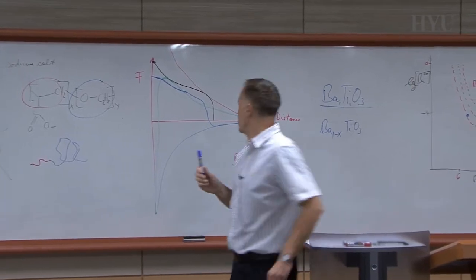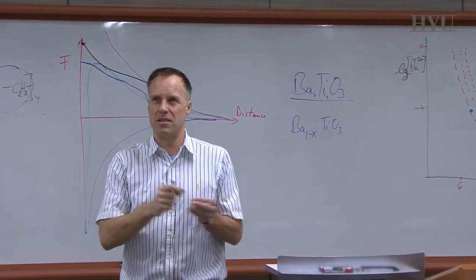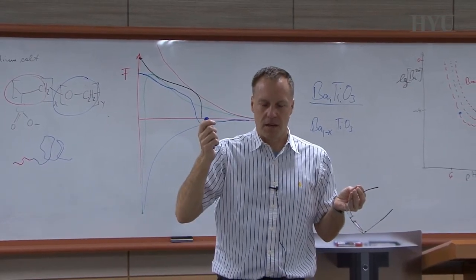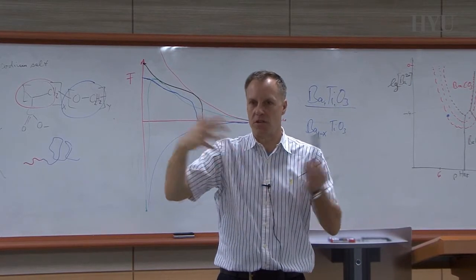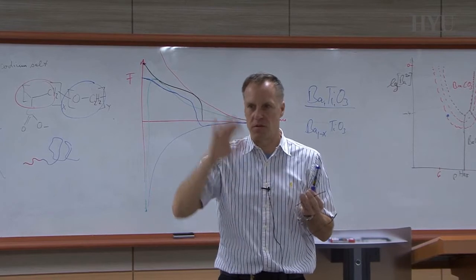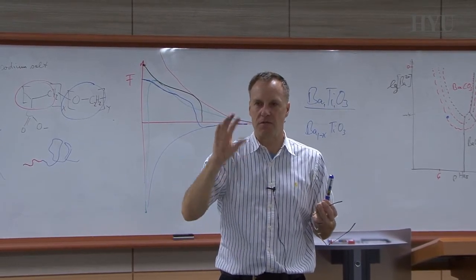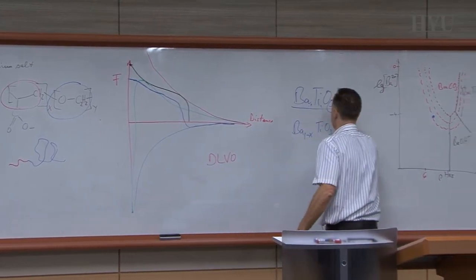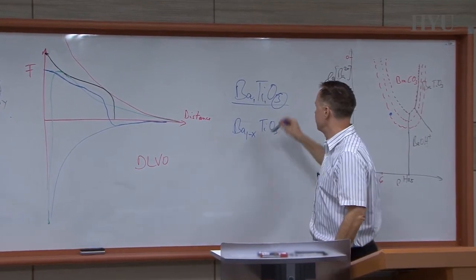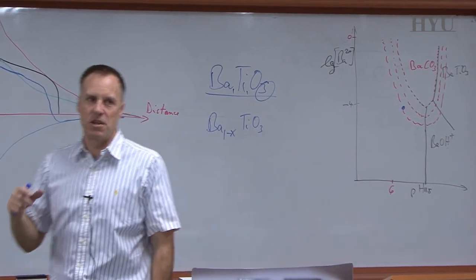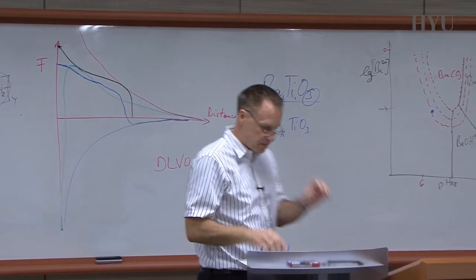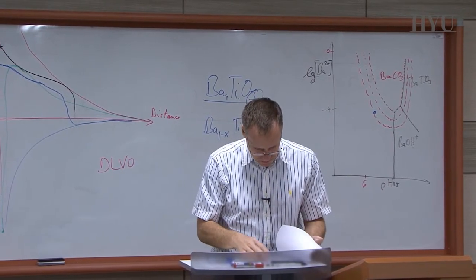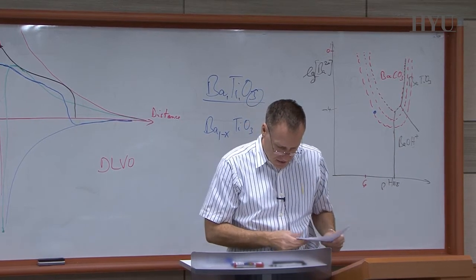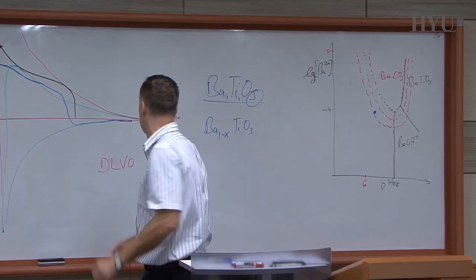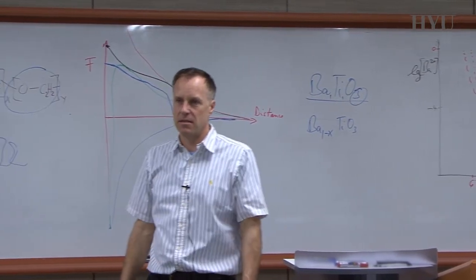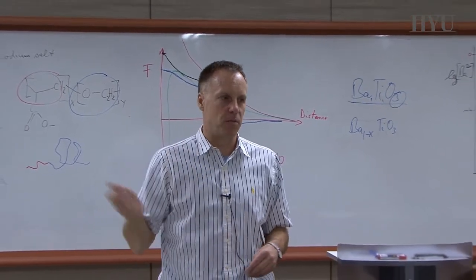Another problem is, we talked about stoichiometry. Of course, you don't have to go through a full sintering process with grain development in these methods, but you deposit your materials always in a certain oxygen environment. So it's a low partial pressure of everything, so you use a vacuum, of course. But the oxygen partial pressure defines how much is in this part in your equation. And of course, now your oxygen might not be stoichiometric all the time, so you achieve very different properties. And what people publish is actually then something on the order of maximum of 1,000 for the dielectric constant, but typically more on the order of 200 for the dielectric constant of barium or strontium titanates when you deposit them through these new methods. Yeah? So you see there's a lot of development still needed.